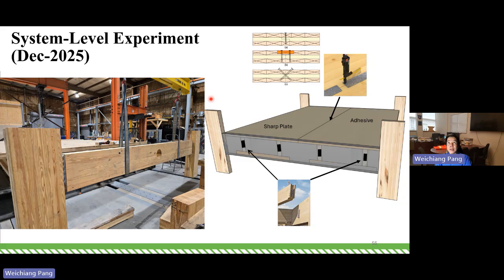In my opinion, yes, if you can retain the option of taking apart the CLT panel and glulam, it's good. However, I foresee this system being used as a full cassette. You just leave the full cassette and move it to another new structure or building to reuse it. So in that case, there's no need to take apart the CLT panel and the glulam. But it's a good point. Our test is a destructive test, so the glue bond had already been damaged, and that's why it was much easier to deconstruct. However, on the other hand, the screws are actually much more difficult to take apart because some of them are already bent into double shear and so on. Yeah, that was a good observation.